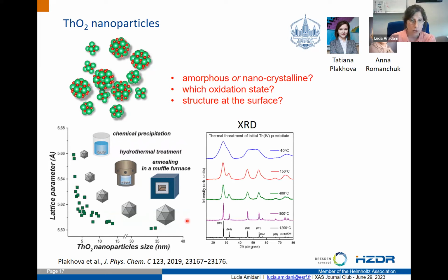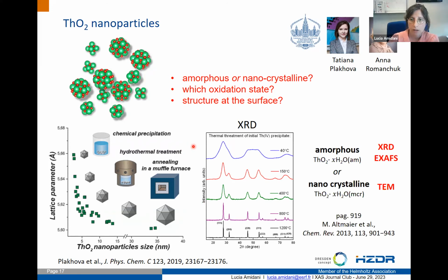Of course, the first thing we look at is the XRD, and we notice immediately that when the nanoparticles are very small, the XRD pattern is not really well defined. And then it becomes more defined, and this is quite a classic example. Actually, it is quite debated what the first stages of nanoparticle synthesis are.